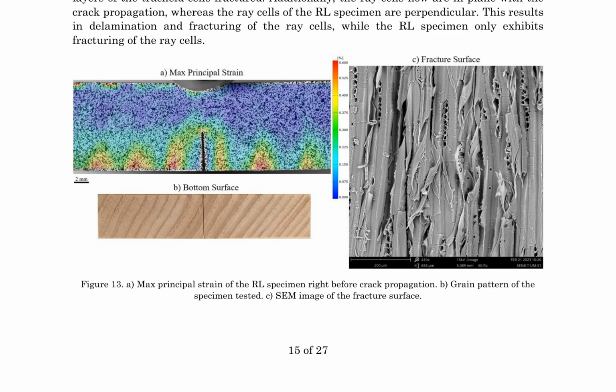This difference in fracture behavior is attributed to the orientation of ray cells relative to the crack propagation direction. In RL specimens, ray cells are perpendicular to the crack, resulting in fracturing of these cells. In contrast, ray cells in TL specimens are in plane with the crack propagation, causing delamination and fracturing of the ray cells. The calculation of initial and total fracture energies was performed using an exponential decay function to extrapolate the stress beyond the measured softening curve.